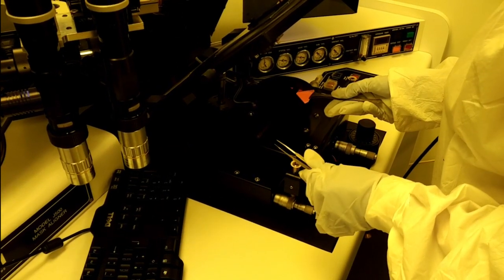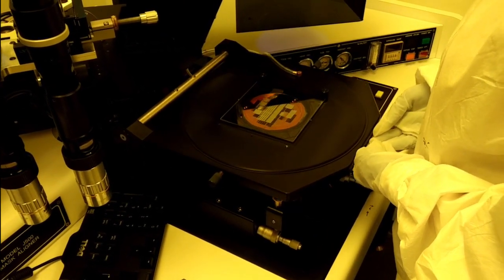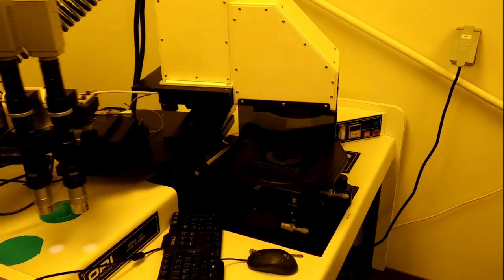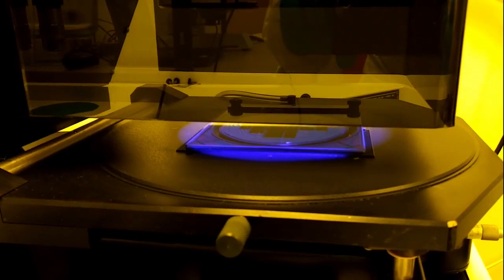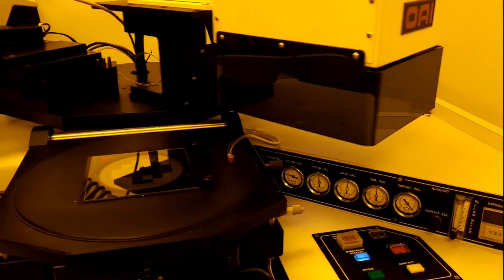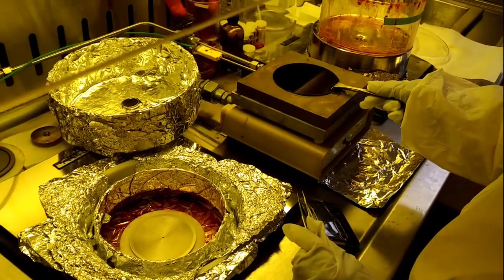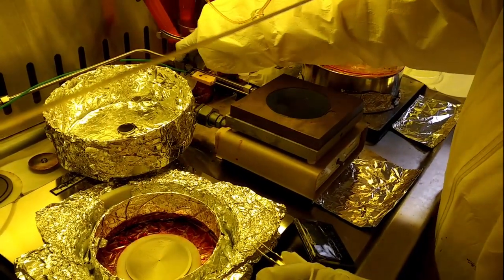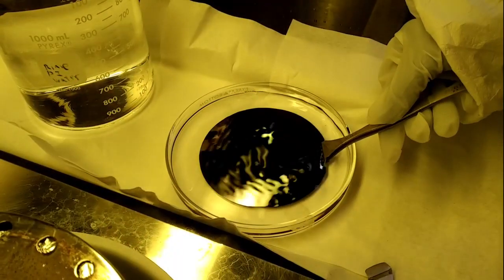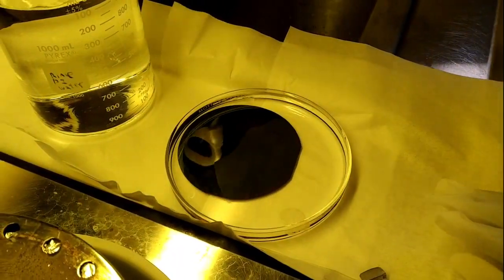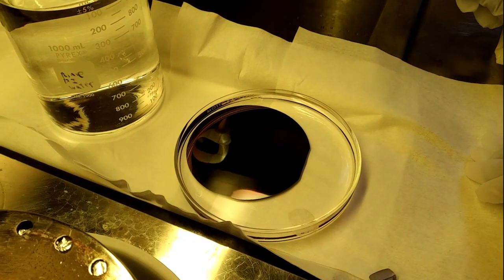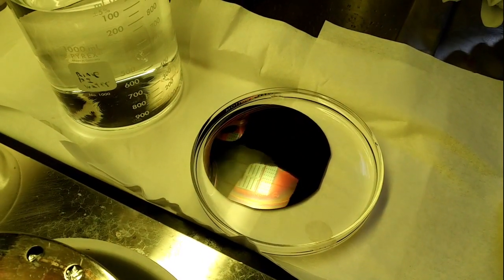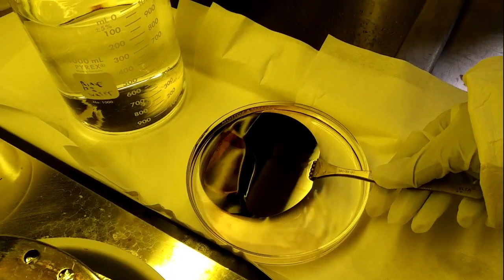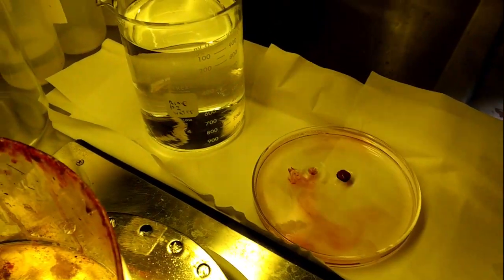Next, the wafer is moved into the mask aligner to expose the mask 1 pattern onto the photoresist using UV light for 240 seconds. The wafer is then moved back to the heater for a 2-minute post-bake with vacuum applied. Next, the wafer is dipped in the developer for around a minute to develop the pattern on the wafer. The wafer is carefully washed in DI water to stop the development from proceeding.